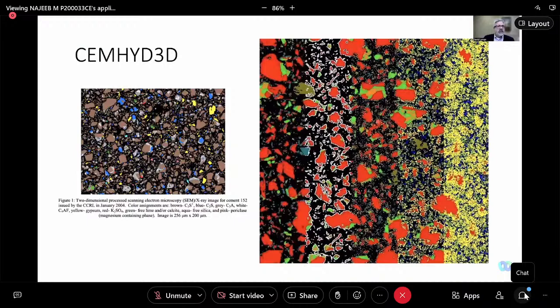Here's some more pictures from those early models. This is how you would, on the left, you see the structure they started with. This is a picture in 3D, or the volume is 3D, but you see the colors identify what phase is in the raw mixture of cement and water. And then with time, you see the time steps on the right, where you take the cement, you identify interfaces, you create ions in the open space in water, you react the cementitious reactions, and you create new product, which is shown in yellow then at the final right side of the diagram. So in the end, these pictures were strikingly realistic. And many researchers found it useful for advancing their understanding of microstructure development.